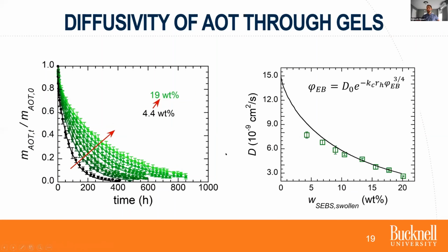And instead of those first order rate constants, we extract diffusivities of AOT reverse micelles through the gels, as indicated by the dark green points here. And so just like before, except I think the experimental parameter is a little bit less empirical, since we have diffusivity as a function of triblock copolymer concentration in the gels, we can model it using one of various different solute diffusion models through gels. In this case, this is a hydrodynamic model for a homogeneous gel, which we feel our materials fit well for that type of model. And you can see the fit is pretty good.